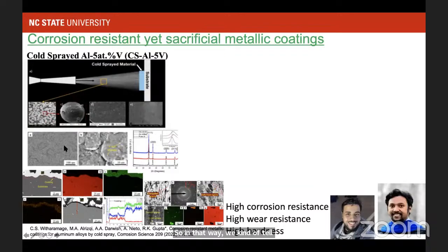So here is one example for aluminum vanadium. What we did is just cold spray and cover the whole surface with that vanadium alloy. It was a really thin layer. So you see the example over here, a very thin coating, like 5 to 20 micron thick, and it was nanocrystalline and things like that. We did all the microscopic characterization and so on.